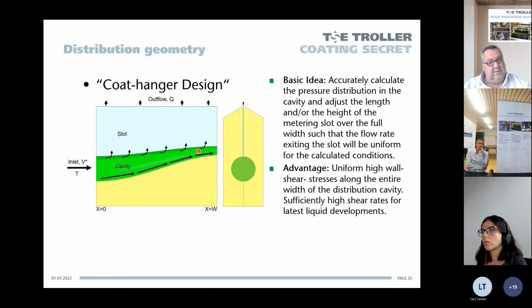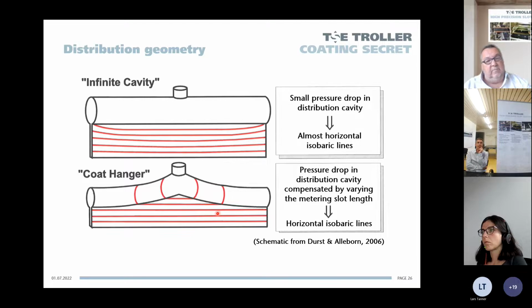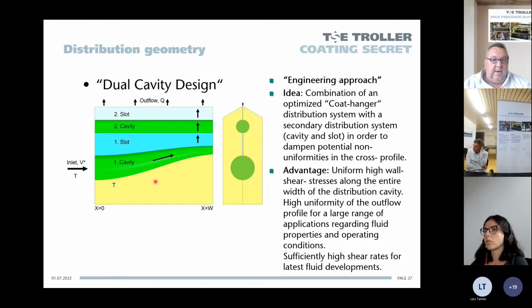Of course, such a system is perfect in the uniformity, but unfortunately, it's not allowing a large range of different products. And this is why we typically combine this coat hanger design, first cavity and first slot, with a second cavity and a second slot. Again, this is either a side fed die or one half of a center fed die. But you see the cross section here. So we have both cavities and the two slots. And with that, we achieve a good self-cleaning behavior combined with an excellent crossweb uniformity over a pretty large range of different applications.